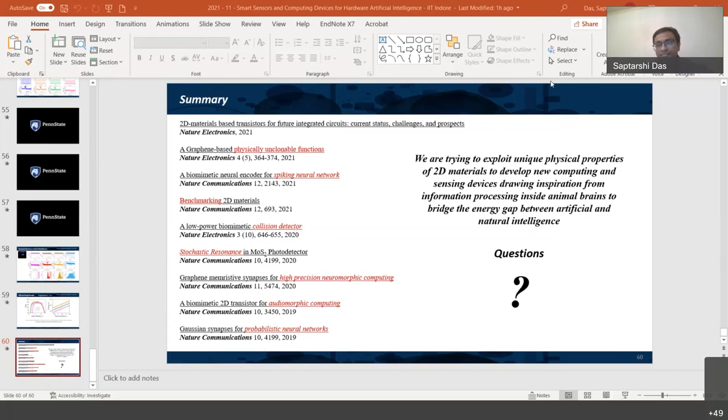Thank you, sir. Sir, S. Srinivasan is asking whether it is stable with humidity and temperature changes. That's an excellent question. So for the temperature, we have really looked into typical temperature ranges that an integrated circuit will be working on, let's say from minus 25 degrees centigrade to 100 degrees centigrade. There you will probably not see a lot of changes in the performance. Again, it depends upon the application. So temperature wise, the devices are quite stable. In fact, MoS2 will be stable even up to like 200 degrees centigrade. And if you cool it down, the challenges are even less.